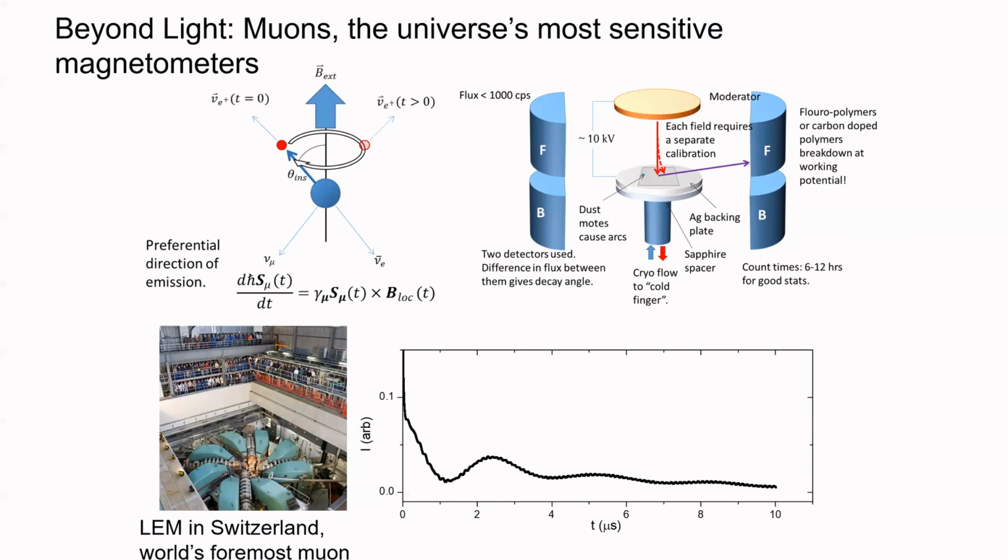And so our most famous example of this is when Dr. Cespedes and his PhD students and an MPhil student realized that at the interface between C60 and copper, that interface became magnetic, even though neither C60 nor copper are magnetic. And so we actually were able to show that was what was going on, partly through this muon experiment,